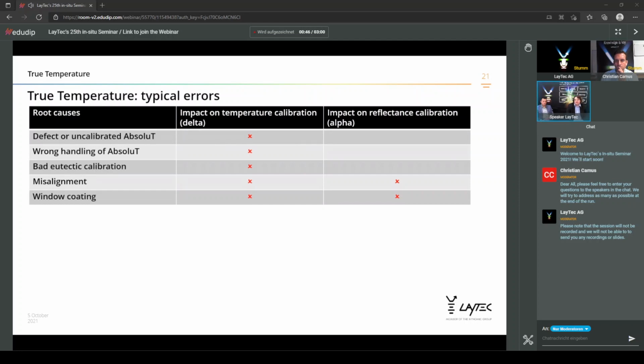Window coating is more or less inherent with the deposition process of the MOCVD process itself. A slight window coating is a typical gradual effect from run to run, over a run cycle sequence between scheduled maintenance periods.